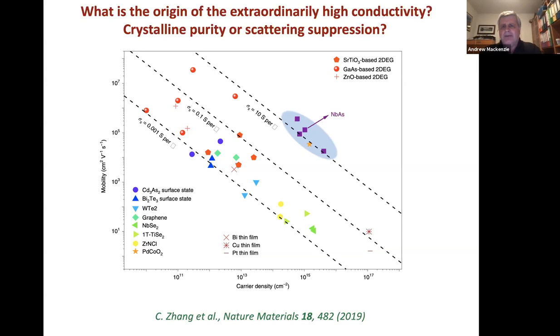And there, you're not seeing it because of crystalline purity. There's no evidence that these are particularly pure materials. You're seeing it because the same underlying physics that gives you topological responses also gives you protection from scattering in some of these surface states. So you don't see a very strong resistive scattering rate because those scattering events are not allowed to take place. Palladium cobaltate sits right in among their results for niobium arsenide. So the question is, is it because of scattering suppression, or is it because of really amazing, genuine material purity?